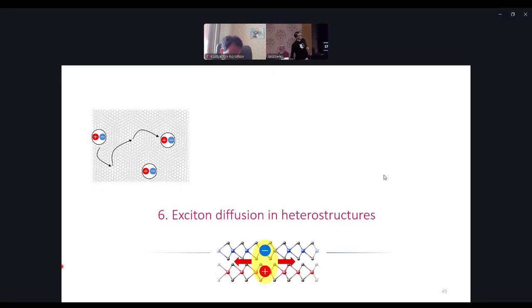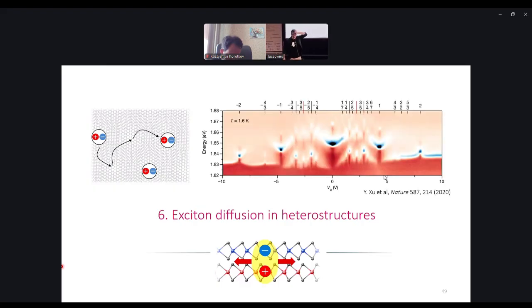In these systems, there are not only this type of indirect excitons, but also, and this is something that you will hear from Kim van Mark on, I think on Tuesday, physics related, how excitons can be used to measure correlated states. I will not explain this plot here. It will take us another couple of minutes. But what it means in the end is that if excitons are sensitive to external screening, then one can think about much more than just the effect of the static screening. You can now think about screening from correlated or uncorrelated states that live in close proximity to the exciton gas, using excitons as sensors. Again, you will hear about it in a couple of days.